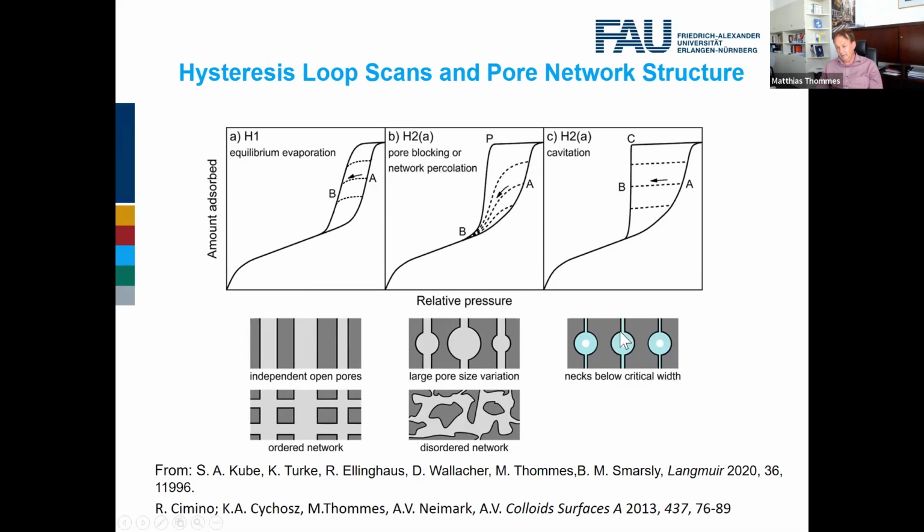If you have cavitation, then of course the environment of a cavity doesn't play any role, because the evaporation of the liquid from the cavity is entirely controlled by the thermodynamics of the confined fluid in the cavity. Essentially, it will go out through bubble formation, through cavitation, when you reach the liquid-vapor spinodal, and it doesn't care what the connectivity says. So in this case, the scanning curves again look very similar to the boundary curves, and very similar to the situation where you have a system of quasi-independent pores. Of course, you have a pore network here, but the mechanism determines the scanning curves.